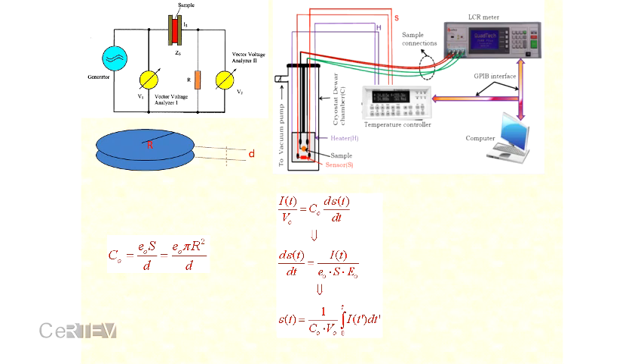Now, before proceeding further, I want to give you a glimpse of the experimental measurement technique. How can we measure the electrical conductivity, which may be DC or AC? For electronic conductivity, we can apply a DC voltage and measure current, so we can get resistance. For ionic conductivity, there is no problem, because in every electrical measurement we have to make a structure. We have to apply electrodes, and then there will be no problem of contact. But for AC measurements, we also use the same structure, with the material sandwiched between two electrodes, and we apply an AC electric field. And this gives us the capacitance as well as the conductance of these materials. I am not going into details of how these equipments work, but